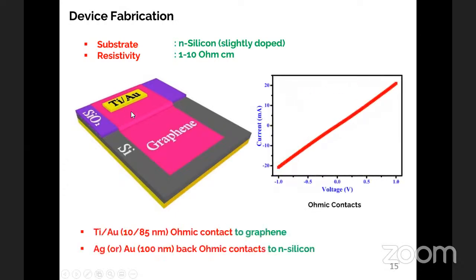Meanwhile, the ohmic contacts to graphene can be made with titanium and gold, and ohmic contacts to silicon can be made with silver or gold, because in any electronic circuit, ohmic contacts are mandatory. Ohmic contacts are nothing but, for example, if you apply 1 volt, the ohmic contact will supply the 1 volt to the graphene without any change in its value. If this is not ohmic but has some barrier, then if you apply 1 volt, the 1 volt will not go to the graphene perfectly. There is some drop in voltage at this interface, so you will not get the perfect results. Of course, the graphene-silicon interface should be a Schottky barrier, but the ohmic contact should not be Schottky. So that's the point here. The ohmic contact is essential in any kind of device, even though it is a Schottky barrier device.